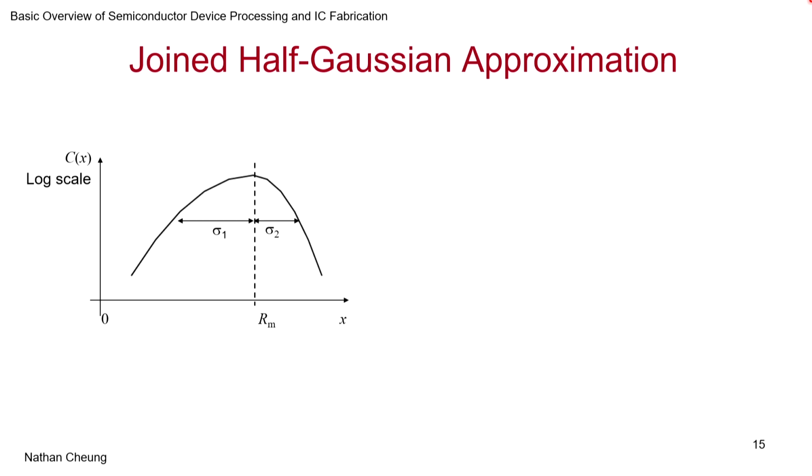We can go for a 3-parameter model. A 3-parameter model, one way is to find the skewness and try to fit it, but a simpler way would be to assume there are two Gaussians. There is a peak value, there is one Gaussian here with a sigma 2 and one Gaussian with a sigma 1. Okay, and this can end up telling you what the distribution can be.